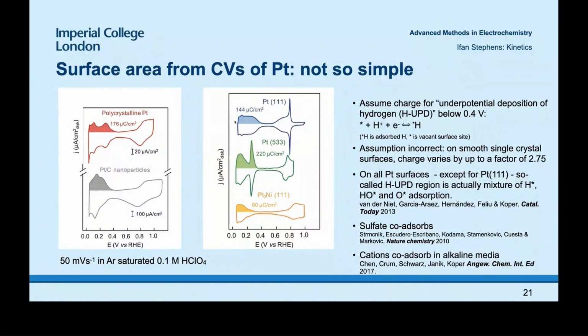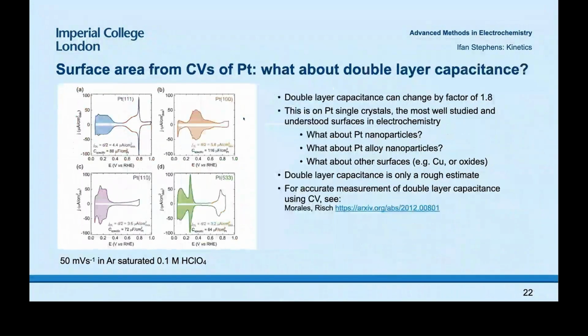Part of the reason for this is that in the region which we usually assign to hydrogen absorption, at least on other surfaces, let's say stepped platinum surfaces, or platinum 110, it's not actually purely hydrogen. You also have oxygen and OH absorbing where hydrogen desorbs. So that's one of the reasons why you can see a much higher current here. Also, you might get sulfate co-absorption, which also complicates things. And cations can co-absorb in alkaline media. That also complicates the charge you end up getting out of these measurements.